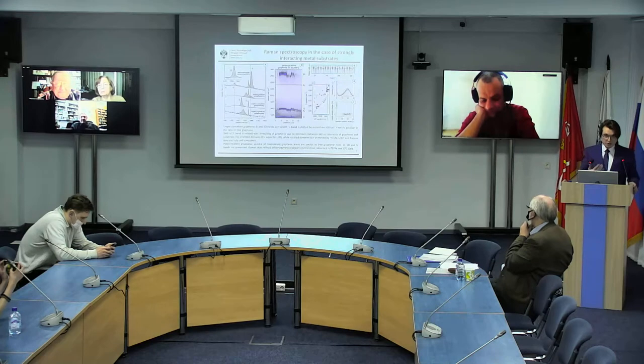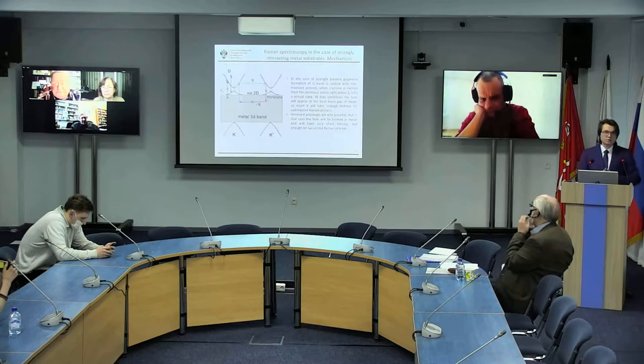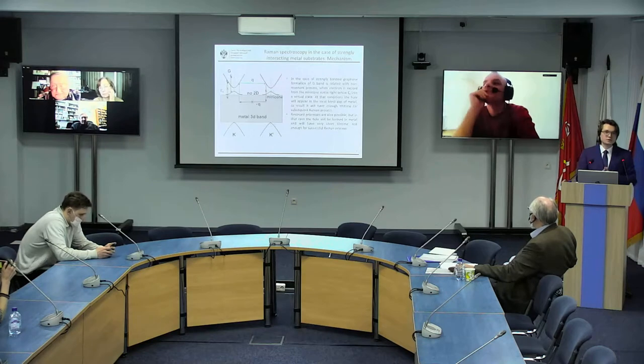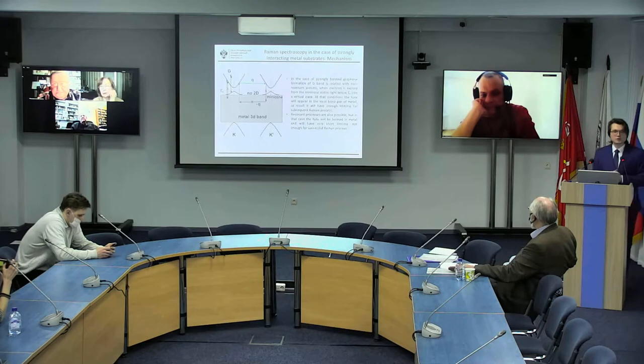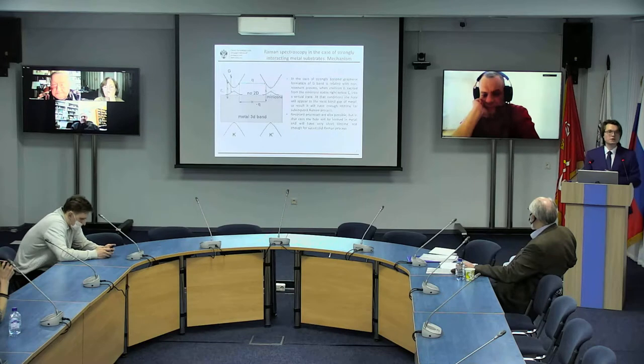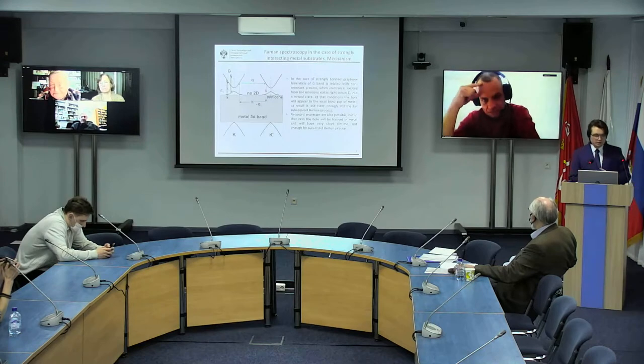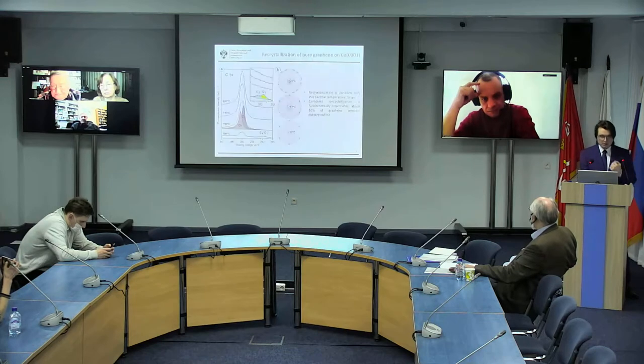As for the presence of the G-band in the spectra, that's not associated with oxygen. The more so, the discussion was on why it actually exists in the case of bound graphene, because the D and 2D bands, as we know, are associated with resonance processes, and the G-band can form as a result of a non-resonance process. And here, it's of particular importance to see the presence of a mini cone of graphene states near the Fermi level, where we can see this transition of electrons. And it's of particular importance that this mini cone is found in the band gap of the metal, in the local band gap. So it has nothing to do with air.